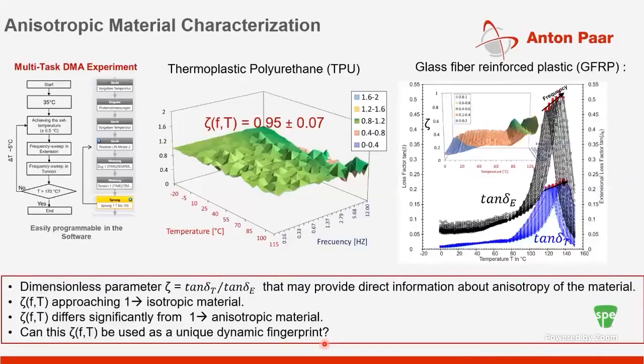Now let's take it a step further. One could compute - since you're measuring loss factors in shear and in torsion, doing oscillations both in rotation and in the axial mode, you basically get loss factors - one can compute something called zeta, which is the ratio of the loss factors measured in torsion to the loss factors measured in extension.